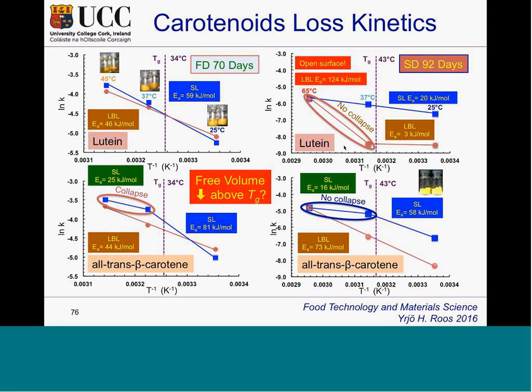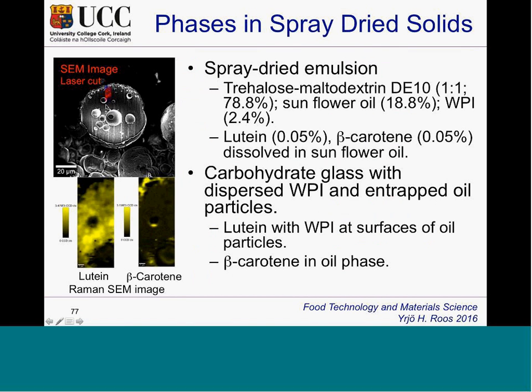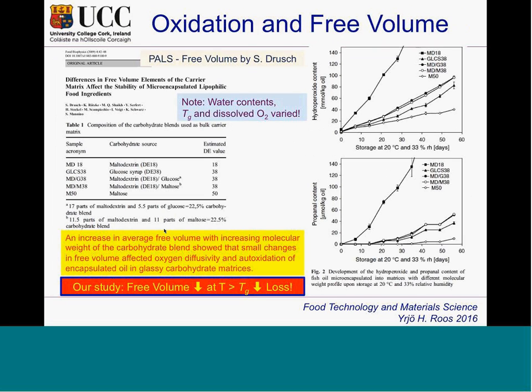This is a Raman image of a particle that has no internal structure, with some voids that are air, and then there are dispersed particles with the carotene. But if we look at these, lutein is mainly on the protein surfaces. We can easily see that. But beta-carotene is not that visible because it's immersed in the oil, and we cannot see that in the image. So we will then claim that the lutein in the system is a sort of antioxidant. It is up front, first to meet the radicals coming into the system, and it changes, disappears because of that.